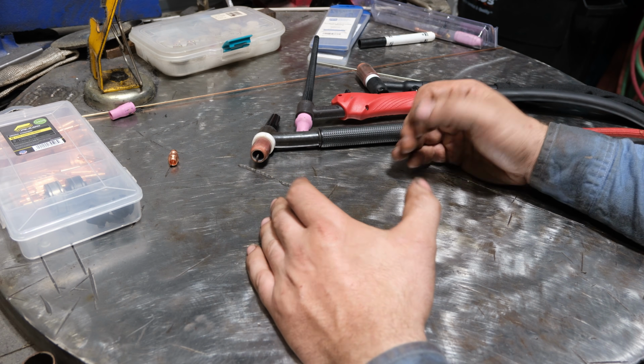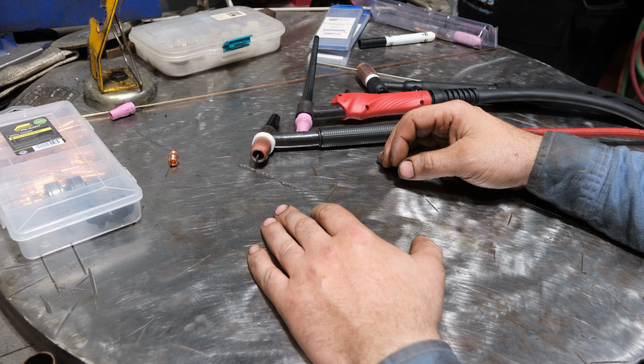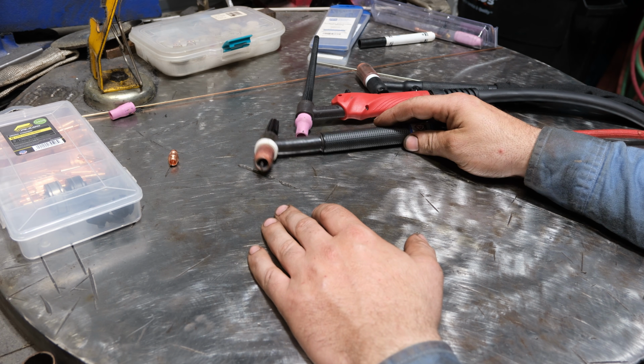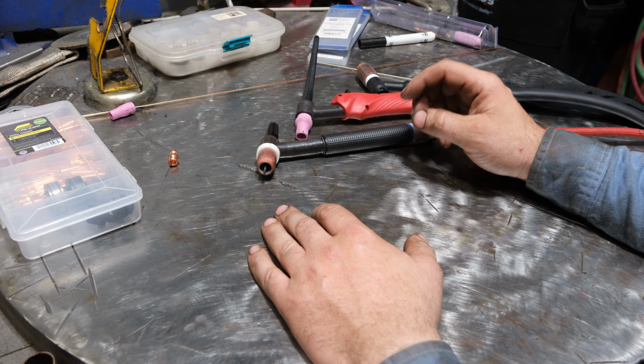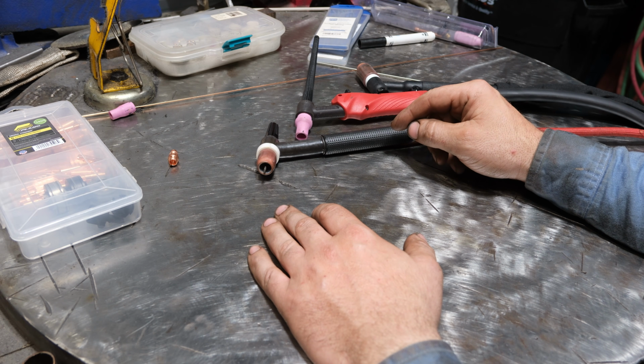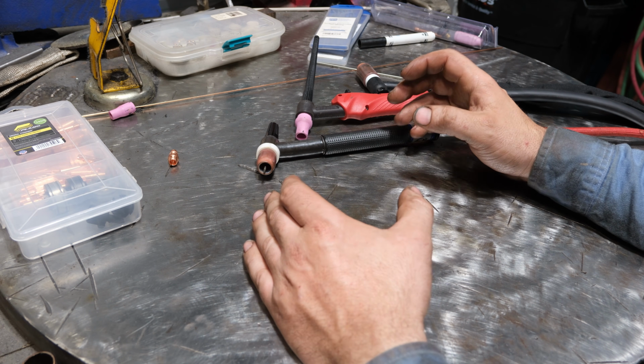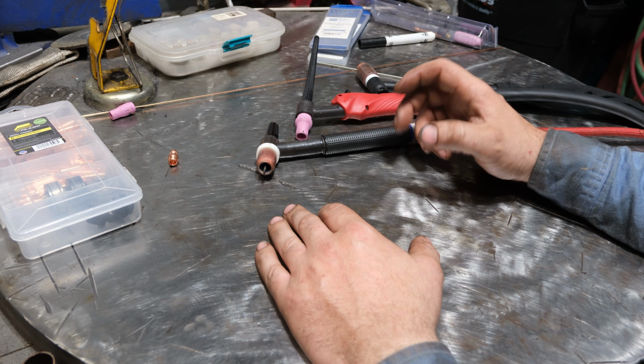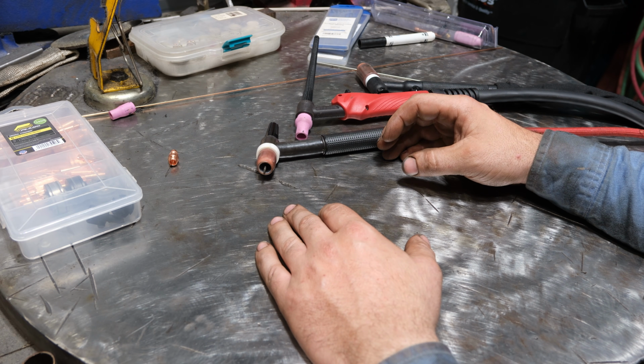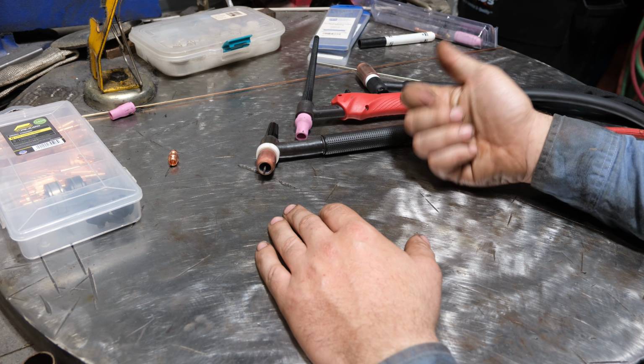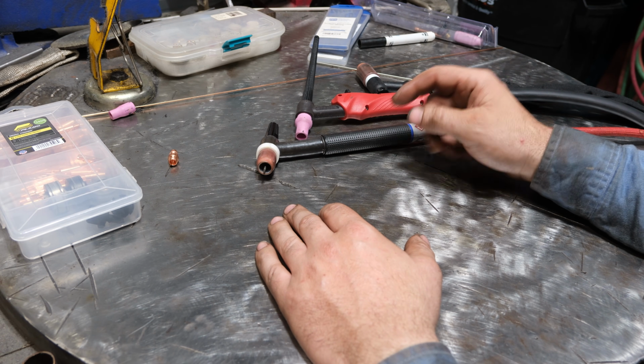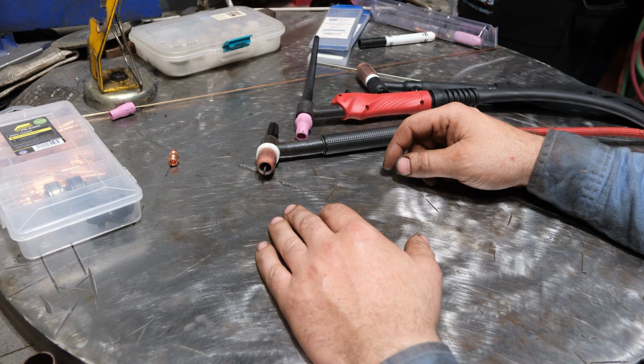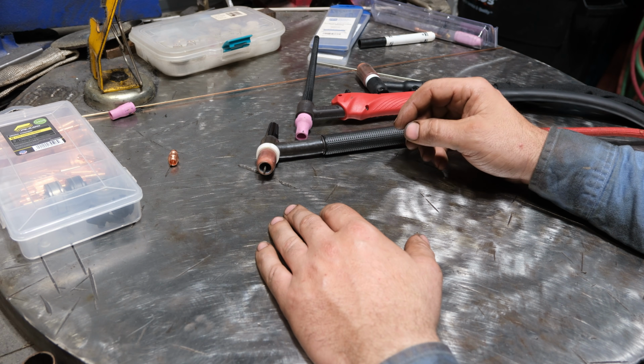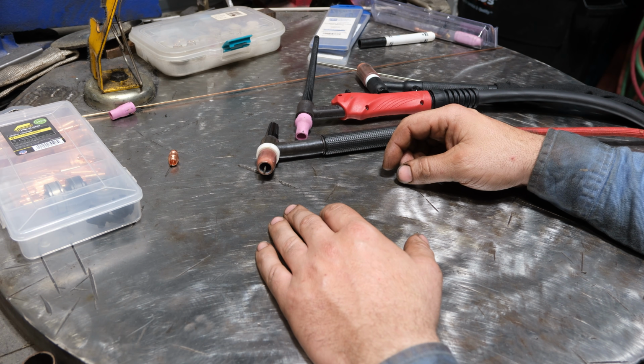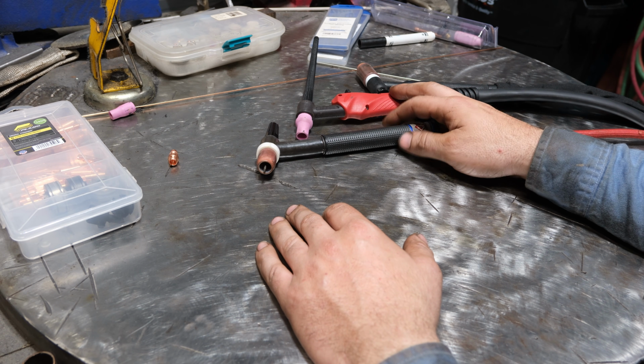The second, and honestly my opinion on what the biggest drawback is, it does not handle surface contamination well at all. Even mill scale on steel will cause it to weld poorly. So your material must be clean, bright, shiny steel or aluminum, whatever it is that you're welding on. You are not welding over oil, rust, grease, any of that. This is incapable of welding over that, so it must be clean, and for a lot of stuff, that's simply not possible. Another downside is the speed that you can weld at.